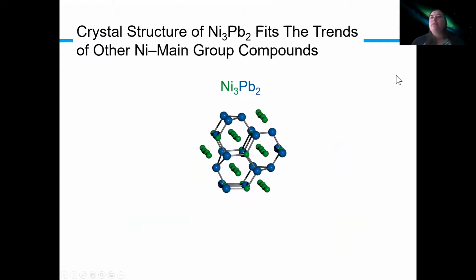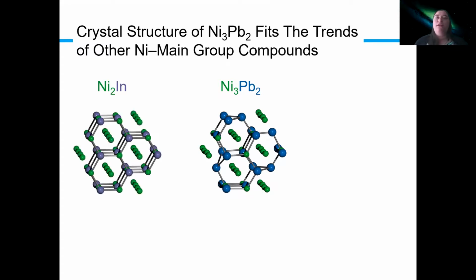From those single crystals, I'm able to determine the structure, and the structure, although related to the P63/mmc B8 type, is actually a modulated structure. And this modulated structure is best understood in comparison to the known B8 type compounds. And so this is nickel 2 indium.